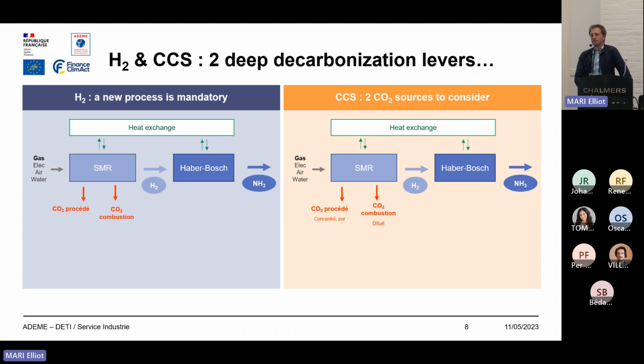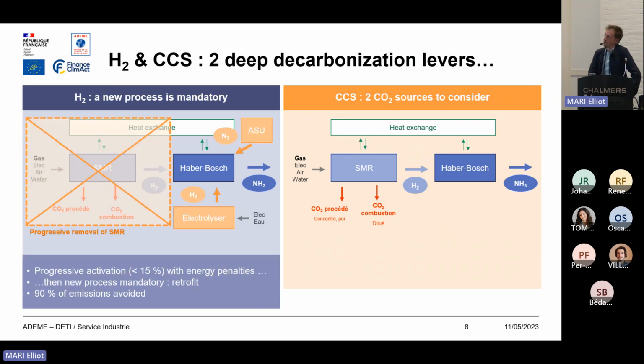So actually, we have a few decarbonization levers: of course energy efficiency, small electrification, and also the removal of nitrous oxide from the nitric acid production, but they are limited in terms of potential. So if we want to achieve a deep decarbonization of ammonia, we have actually two ways. The first way is the hydrogen way, which requires a new process. If you want to go this way, you need to close the steam methane reformer and replace it with an electrolyzer for hydrogen, and also the nitrogen, which was brought with the air, now needs an air separation unit to feed the Haber-Bosch process.